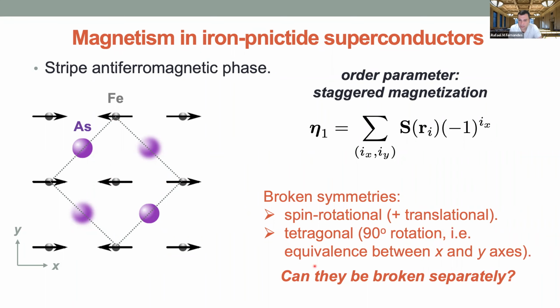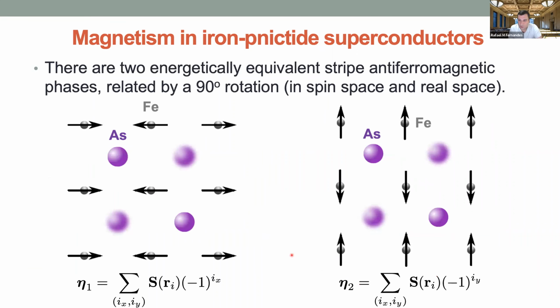The question again is, can they be broken separately, these 2 symmetries? To construct a theory, we need to realize there are actually 2 different magnetic ground states that are degenerate. One is when the spins are parallel along Y and anti-parallel along X, that's what I call eta1. The other is when the spins are parallel along X and anti-parallel along Y, that's eta2. They are related by—you see that I cannot just do a spin rotation to go from one to another. I need to do a spin rotation and a real space 90-degree rotation.